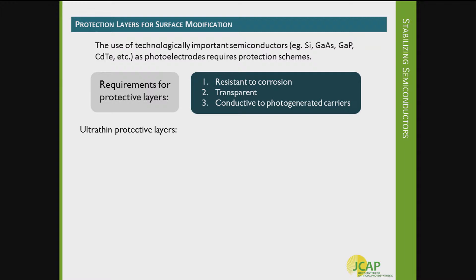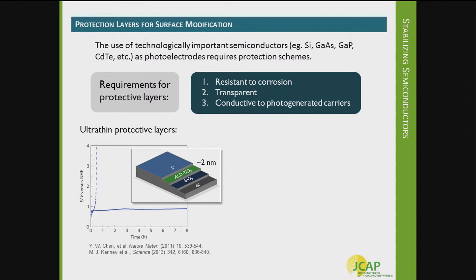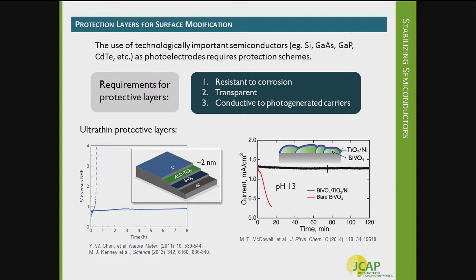There's been quite a bit of successful work in recent years focused on ultra-thin protective layers deposited with techniques like atomic layer deposition. This is data from Stanford where ultra-thin TiO2, on the order of a few nanometers, was used to protect silicon photoanodes — improving stability from less than an hour to about eight hours. I've also worked in this area coating bismuth vanadate with ultra-thin TiO2 films to enhance lifetime. But overall, ultra-thin films always run into photo corrosion problems after 5 to 20 hours due to natural pinholes and defects, making thicker protection layers a necessary direction.